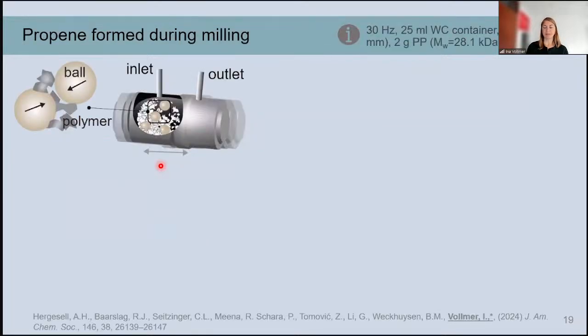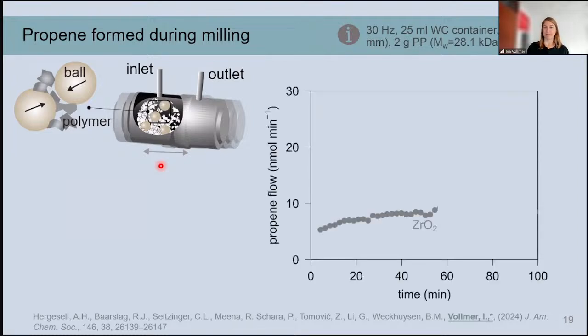So to dive a little bit deeper into this mechanochemical process, we can look at the propene flow over time. This is what we measure on the online GC and what comes out of the reactor together with this stream of nitrogen. And when we turn off the ball mill, this stream of propene immediately stops. And when we start the milling again, then the propene flow also starts up again.